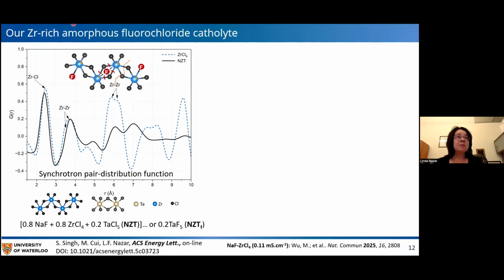So this shows our new zirconium-rich amorphous fluorochloride. So instead of using just a chloride, we decided to incorporate fluorine into the material in order to increase its oxidative stability. And so this shows the optimum composition, which is simply obtained by ball milling for a few hours, not a very long period of time: sodium fluoride, zirconium chloride, and tantalum chloride, and the tantalum chloride can be replaced by tantalum fluoride.